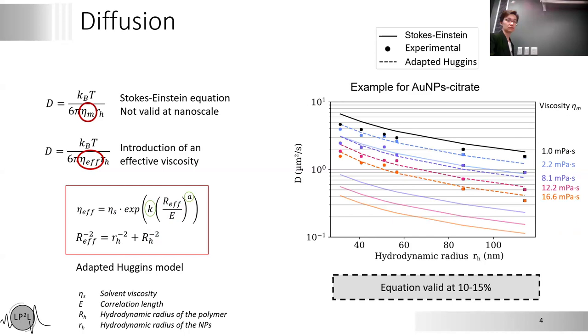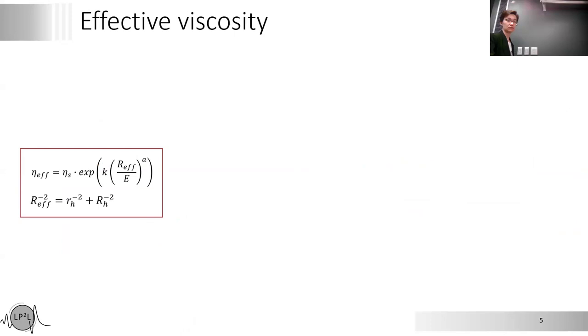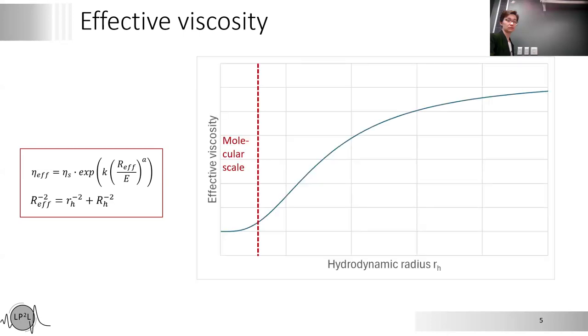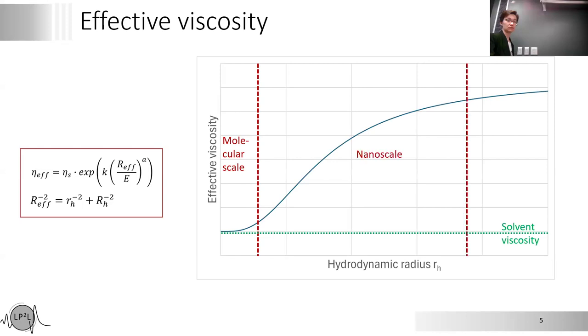And if we come back here, what is really nice with this effective viscosity model is that it allows us to fit the Stokes-Einstein equation for all scales. So for a very small radius compared to the polymer one, at the molecular scale, we have a viscosity which is close to the solvent one. At nanoscale, which is our case, we have a viscosity highly dependent on the hydrodynamic radius of our particles. And at macro scale, we come back to the macroscopic viscosity. So this equation allows us to use the effective viscosity at all scales.